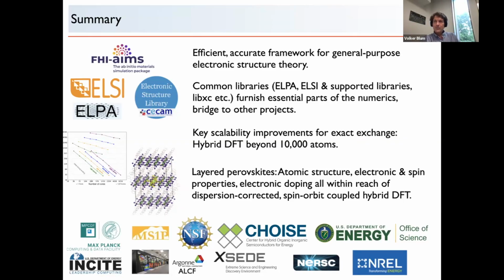For the energy level alignment, we use direct supercell calculations, as I mentioned. We had the same components in the supercell, and so we did not need to do any kind of alignment. We have used core-state alignment in the past, but I believe that you really want to know the interface between the materials explicitly if you want to get the alignment absolutely correct. Core-state alignment is something that we've done between different materials. But normally we rely on the fact that we can put both components into the same supercell, and we don't have to align between different calculations.